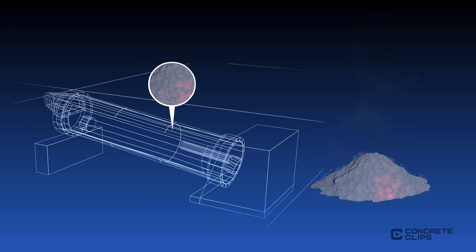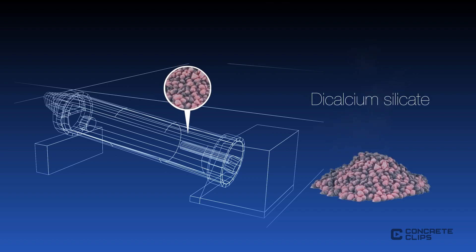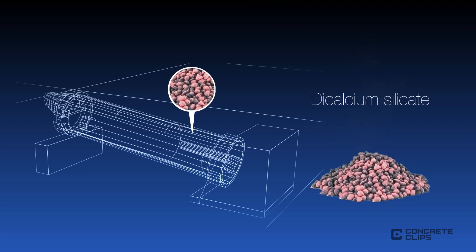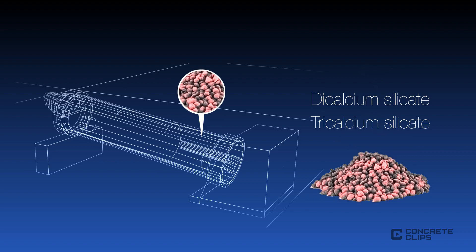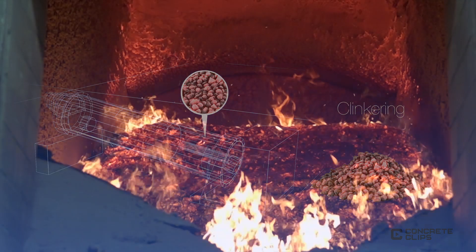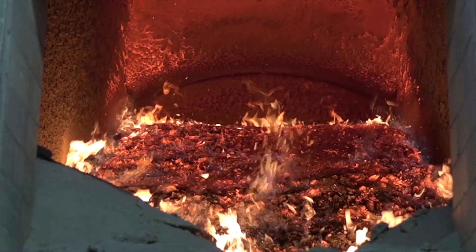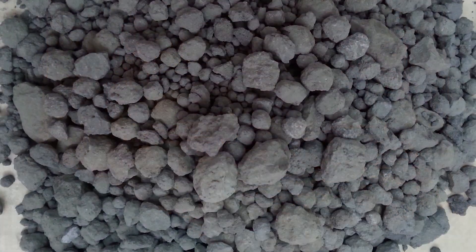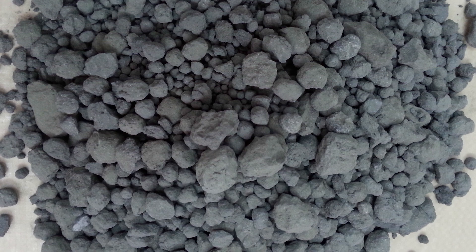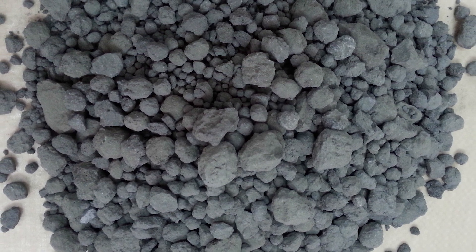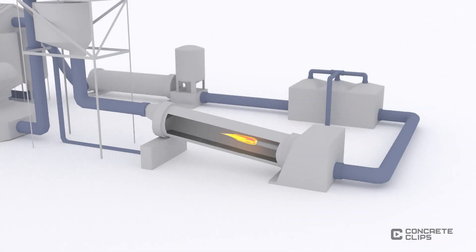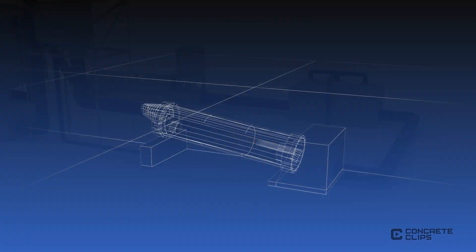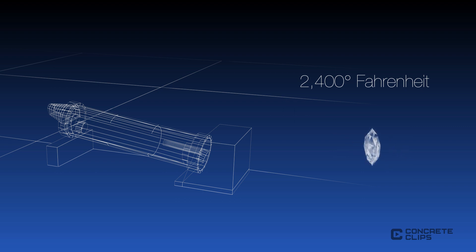With further increase in temperature, Portland cement's two primary constituents, dicalcium silicate and tricalcium silicate, are formed in a process called clinkering. At these temperatures, other compounds melt which causes the mix to conglomerate into lumps or nodules about the size of small marbles called clinker. The most important constituent of Portland cement is formed in the hottest zone at temperatures above 2,400 degrees Fahrenheit. The clinkering process is complete when all the silica is in the silicate crystals and the amount of free calcium oxide is less than 1%.